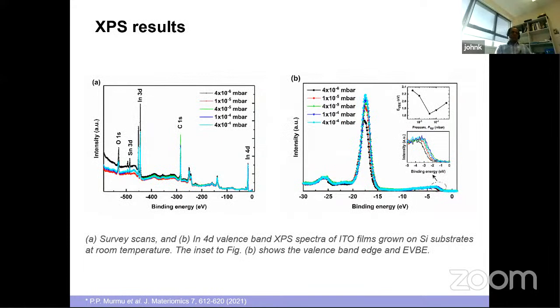Then we tried to understand the band structure, so we looked at it experimentally. We did XPS, synchrotron based XPS, to look at the indium 3d, indium 4d, and all those peaks. The indium 4d core level and valence band edge were estimated by linear extrapolation of the surface peak. You can easily see the valence band shift in the films after annealing, which suggests a change in the Fermi level energies, due to the reverse Moss-Burstein effect, we call it. So there is a change in the band gap as well.